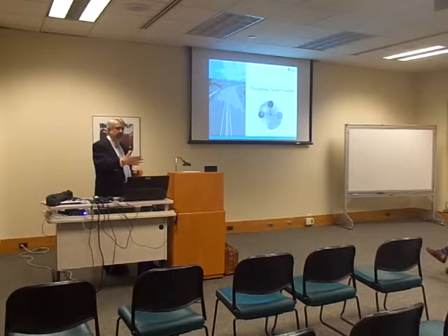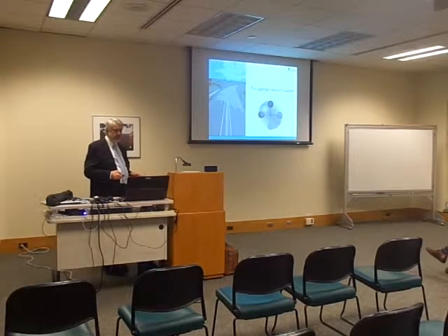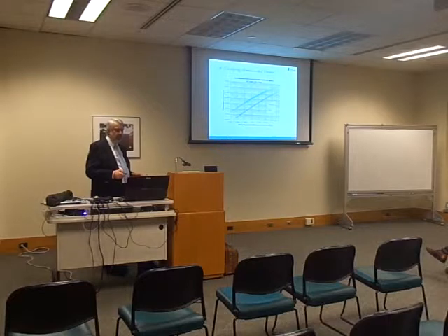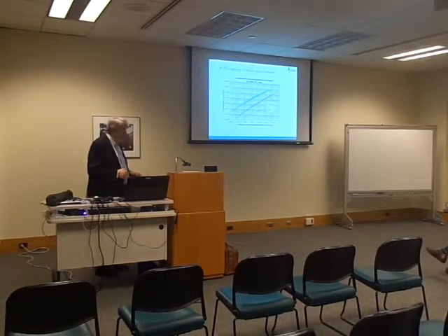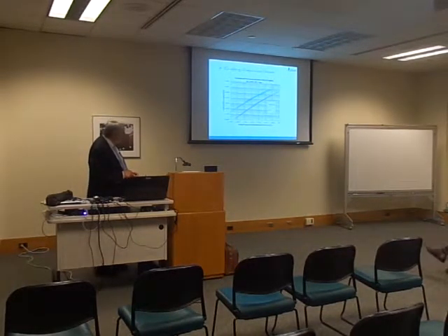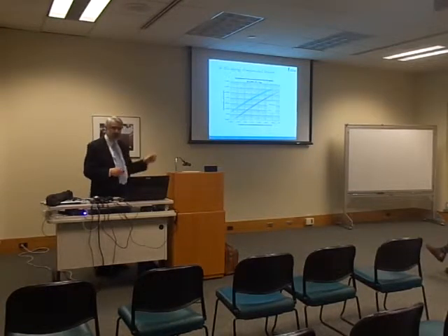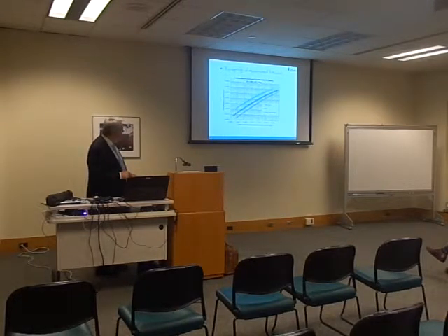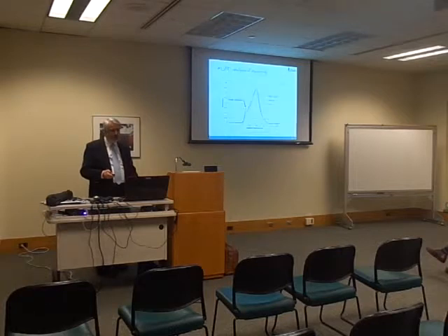Assuming that you rejuvenated something, time will still pass. It means that starting from the original, the aged, we drove it down because of rejuvenation to the desired level. That's what we spoke about before. But because oxygen is still there, because ultraviolet is still there, it will increase. And that's a test, test results, how after some aging process, indeed, it started going back to the aged structure.